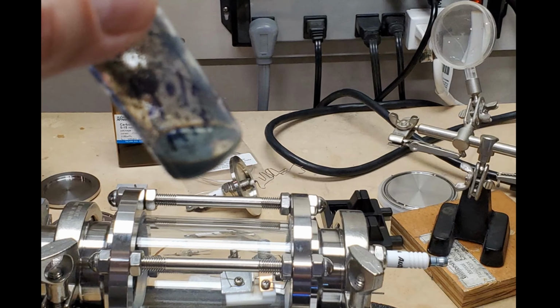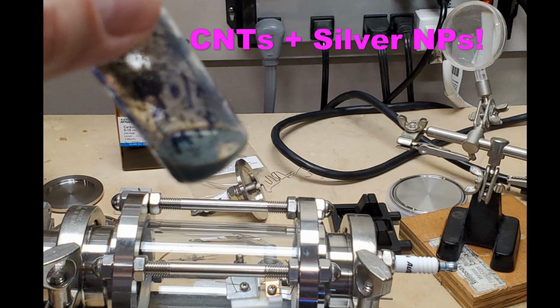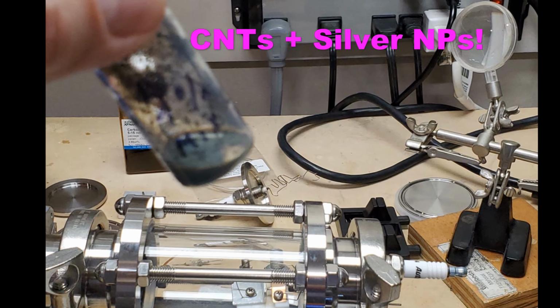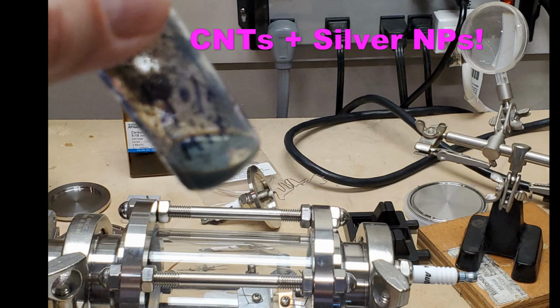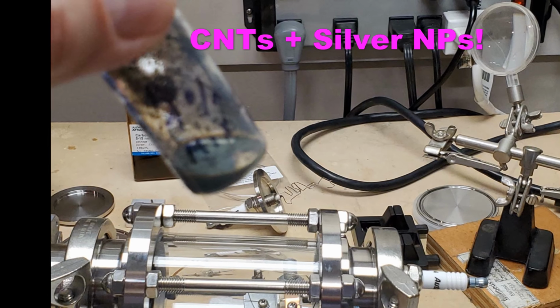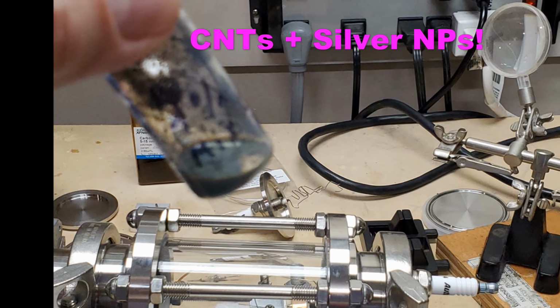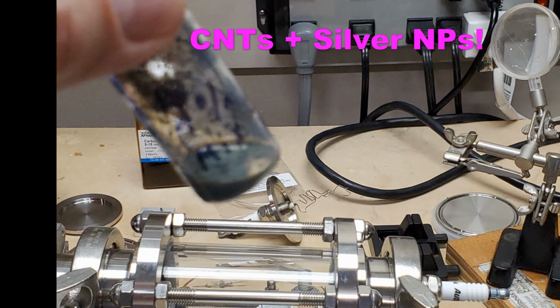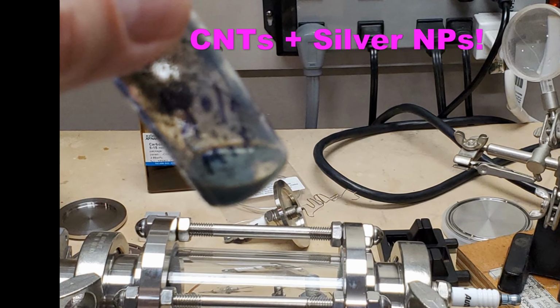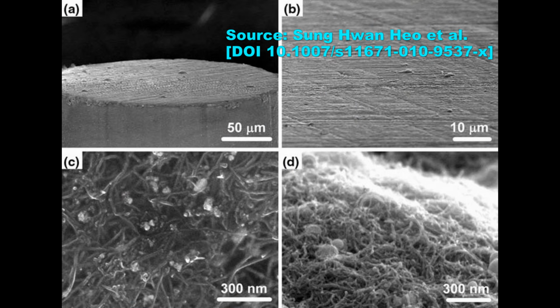Our black slurry is a simple mixture of carbon nanotubes and silver nanoparticles. Carbon nanotubes, or CNTs as we call them, provide the free electrons via field emission, while the silver nanoparticles are used to bond the CNTs to the surface of the metal electrode. This is how the surface of the metal electrode typically looks after applying the mixture of CNTs and nanoparticles. Note the individual CNT fibers visible under the scanning electron microscope. They are the source of the free electrons.